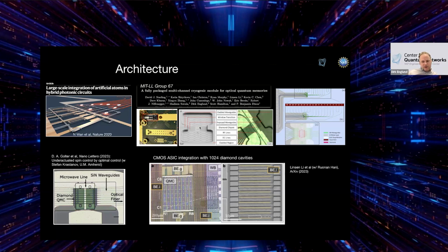that have etched into them sockets, little recesses that go through the top cover oxide of the photonic integrated waveguide circuit. And into these, we can place, in our case by pick and place stamping methods, small chiplets of diamond. And you can see that chiplet here, kind of an outline in the photograph, and here in the schematic. You see there's 8 waveguides coming out that are connected to 8 diamond memory nodes. And the diamond looks like this.